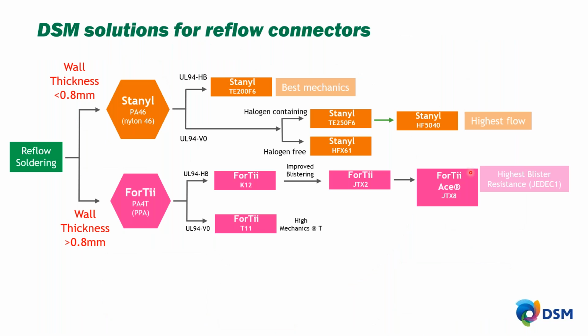So DSM has two product families for this reflow space. The first is the Stanyl product line, the nylon 4-6. It's a straight chain molecule or polymer rather. So it has very good flow characteristics. So it is great for your applications where you have a wall thickness of less than 0.8 millimeters. So for very thin wall applications, Stanyl is a great choice for your on printed circuit board connectors.